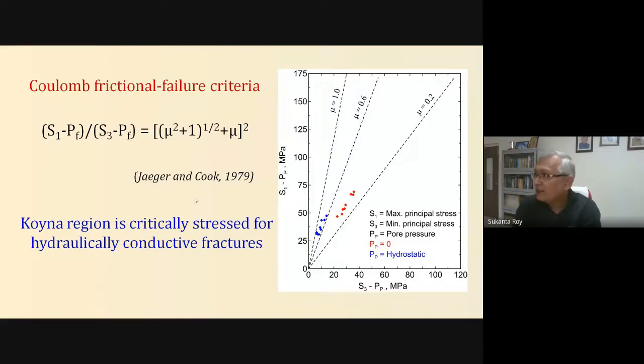And the final figure here is the Coulomb frictional failure criteria. We did some small calculations here. For the continental crust, the mu values, the coefficient of friction, are essentially between 0.6 and 1. And we plotted our stress data on this plot. You can see that if we consider pore pressure as 0, which is shown in red, then our data plots between 0.2 and 0.6 coefficient of friction. Whereas if we take the hydrostatic case, they plot between mu equal to 0.6 and mu equal to 1, which means that the Koyna region is really critically stressed, with 0.6 to 1. So it is critically stressed for hydraulically conductive fractures, whereas for the dry ones, you will need certain other conditions to cause failure.